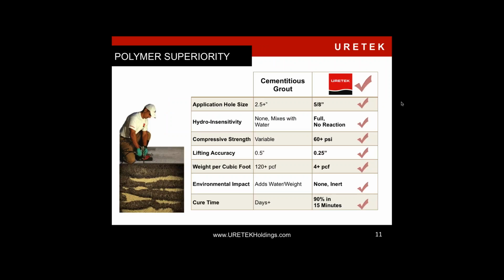So one of the other go-tos used to be cementitious grout for mudjacking, which several people are familiar with. Advantages of using high-density polyurethane: your injection hole is 5/8 of an inch, about the size of your thumb, versus 2.5 inches. You have full reaction of the material, setting up, being hydro-insensitive. In standing water, cementitious grout will not set up. Under dynamic loading, laboratory loads, cementitious grout will fail. So if you're injecting underneath a moving piece of equipment or forklift traffic, cementitious grout will break apart. High-density polyurethane will not. You're able to lift within a quarter, possibly 1/8 of an inch using the high-density polyurethane.